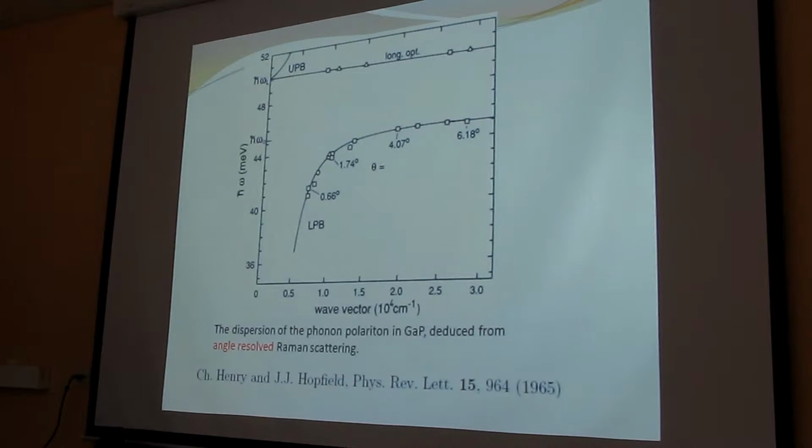These are the numbers given here. The Rabi splitting is about 6 millielectron volts, or maybe 5. There are two quantities to measure the oscillator strength. One would be the transverse-longitudinal splitting, which is what we usually do. This is the difference here. The Rabi splitting would be the minimum vertical distance between the upper and lower branch, which is much higher. So sometimes people confuse these two quantities.